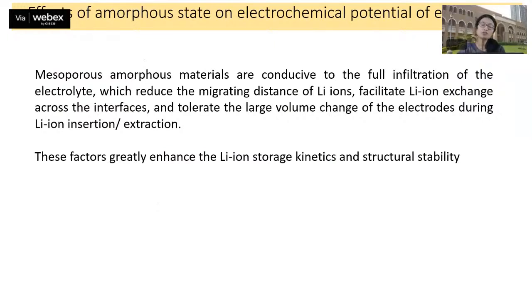But here one point you have to remember is, if it is extremely porous, then it can also lead to some kind of disadvantage. And what is that disadvantage? The disadvantage is it will lead to the formation of a larger amount of SEI. So if a larger amount of SEI forms, in that case, what is going to happen? You will lose your lithium ion in the formation of this SEI. So your initial Coulombic efficiency is going to decrease.